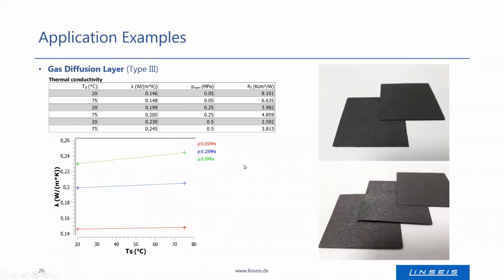Another thing which can be seen very clearly is that the contact resistance, the offset in the graphs, decreases with increasing contact pressure. So from here, from 8 to about 4, decreasing further to about 2.6.